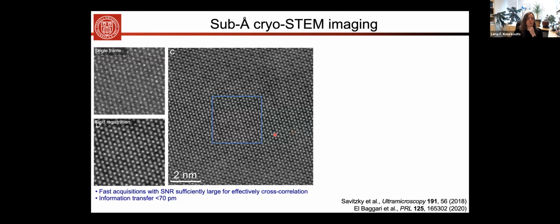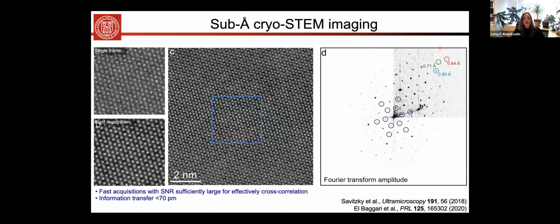Okay, so here you see just one example. These are actually still quite high signal to noise images, but you see that registration of an image series allows you to push up the signal to noise and resolution down to close to 0.6 angstrom, as you can see here in the Fourier transform. So what we can do today in real space, without any averaging over different areas in the sample, in a single area of the specimen, we can image the structure of the material at sub-angstrom resolution. And what this shows in this particular material, this is 1T prime tantalum disulfide, is how it trimerizes as you cool it down into the electronic phase. I don't want to talk too much about this particular system.